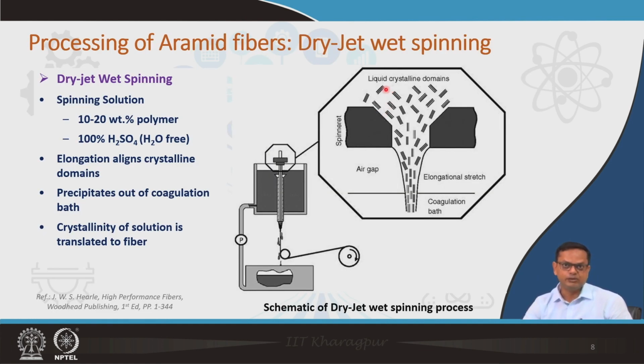You can see here this liquid crystalline state is there, the domains are there. These are all nematic liquid crystalline domains, and now these domains are pulled through this dry jet wet spinning method. You can see there is an air gap of around 1 to 4 centimeter, and through this air gap some evaporation of the solvent takes place. Okay, so that's why it is required. So, this is the dry spinning stage, and then there is a coagulation bath.